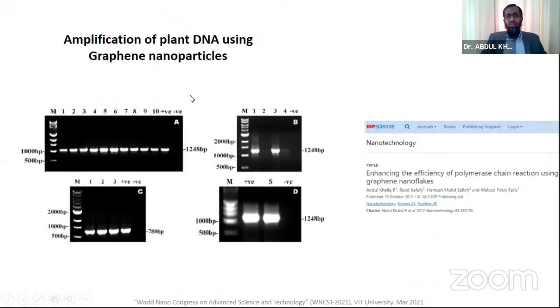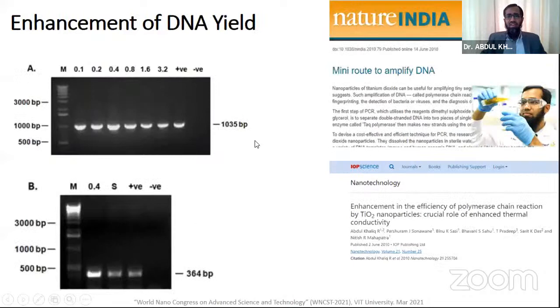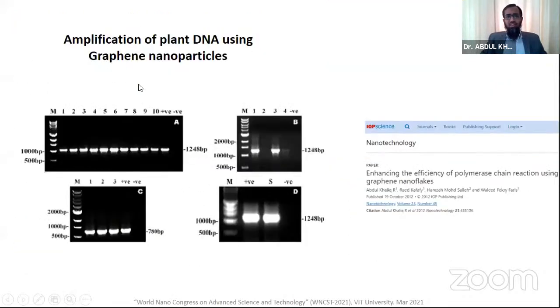Then we used graphene. The previous one was using TiO2 metal oxide; this is graphene based. Similarly here, we found a very nice bell-shaped curve. With lower concentration, you get lower yield. As the concentration goes up, the PCR yield increases, and when you keep increasing the concentration, the yield decreases. This clearly indicates that the effect of concentration of nanoparticles is extremely evident, contrary to all the other mechanisms proposed by the biologists, right?